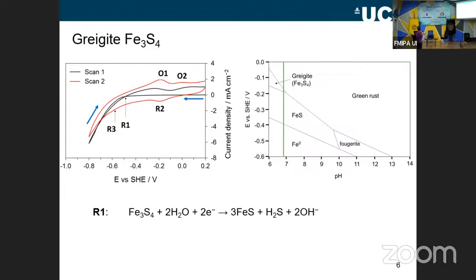So what does that mean is happening on my cyclic voltammogram? As I said, I start to get a reduction reaction happening from R1 here, down here. That's at about minus 0.5 volts. One thing it could be is the reaction of my greigite going to FeS, so it's the iron 3 going to iron 2 here. The diagram predicts it should happen at about minus 0.2, but it might be that the kinetics are very slow, so maybe I need to go to minus 0.5 to get the reaction to happen. So it could be that my reaction is this one, the greigite going to FeS, so just a change in the oxidation state.